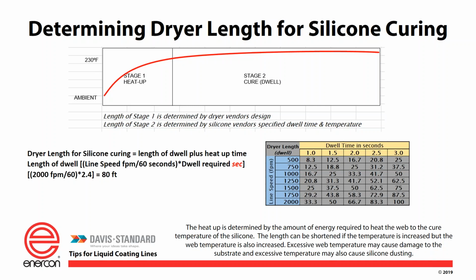For dwell time versus dryer length versus line speed, there's a nice chart here to show you. Let's say I want to run 1,500 feet per minute. You see that 1, 2, 3, 4, 5 down on the blue. And I want to run it for, let's say, 2 seconds at that temperature. So the stage 2 dryer will need to be 50 feet long. And there's a formula to the side there that you can use to calculate your dwell times and your dryer lengths.